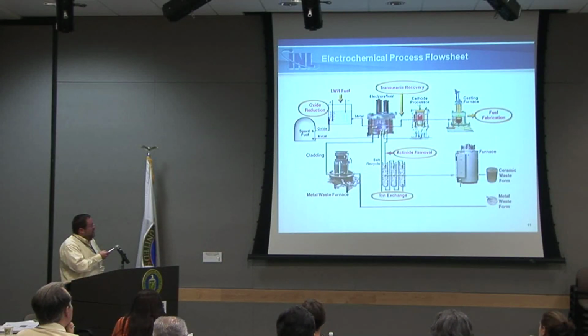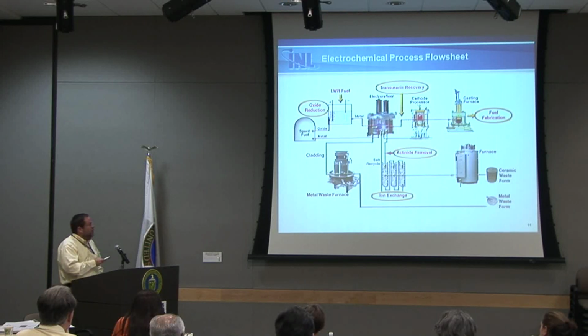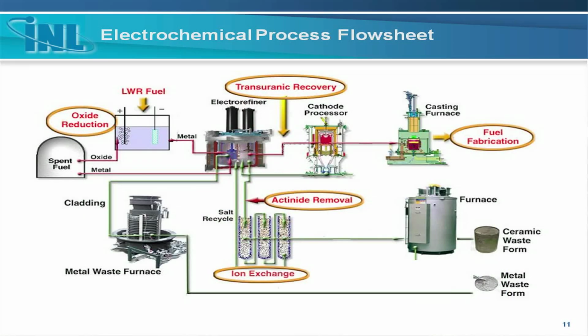But let's say the general process is you take the spent fuel, either the oxide from a commercial fuel and reduce it to metal, or you take metal fuel from a fast reactor, you chop it first, and place it into an electrorefiner, which is the workhorse for electrochemical processing. We'll talk more in detail about the electrorefining operation, but in general, through application of potentials to anodes and cathodes, you can recover the actinide products from this salt system. The actinide products can then go through additional processing in a cathode processor, and you can end up getting a metal product from that which you can use for fabricating fuel.